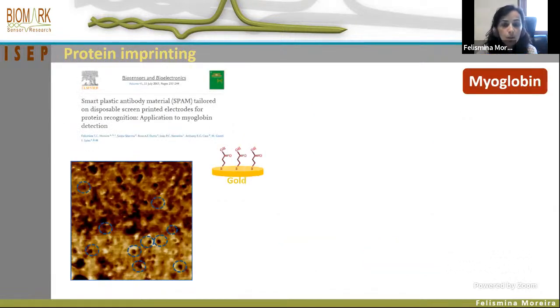And then we moved, when we tried to improve the procedure of the imprinting stage of protein, and we introduced a new concept. We developed a smart plastic antibody material. Then we also used gold screen printed electrodes as a support material. And the first step consists in the modification of the gold electrode with thiol with carboxylic functional groups.